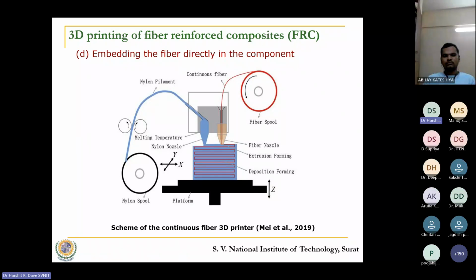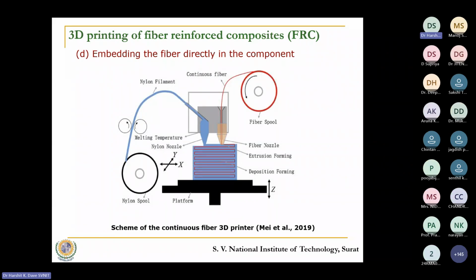What you do is there is no mixing of fiber and the polymer by creating a filament composite. They do not come out together through a single nozzle. But what happens is there are two separate nozzles and both the nozzles operate independently. One is the nozzle for the filament, as you can see, and the other is the nozzle for carbon fiber. And depending on the design that you have selected, depending on the way you have designed each layer to have the fiber or the polymer, the deposition takes place by these two nozzles.